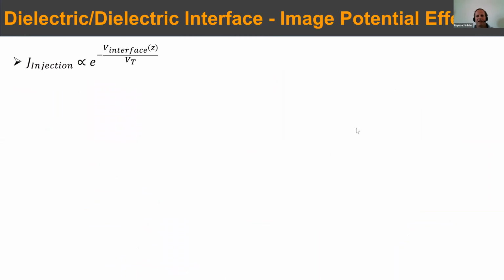Now to the second thing. What happened at the dielectric interface? And here we also went to the equations that people are using for describing charge injection and collection into the device. These equations are usually attributed to Scott and Malliaras and are based on a modification of charge injection at a Schottky contact. Now, what people are doing is assuming that the injection current is proportional to the potential barrier at the interface.